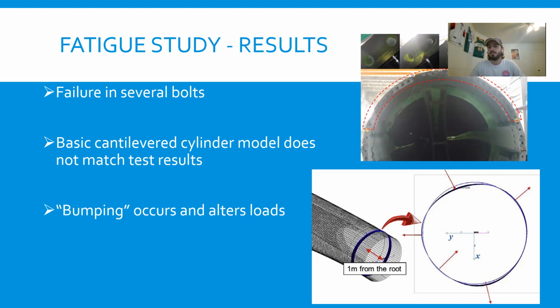During bumping, parts of the cross section of the root are getting elongated and stretched out, and some parts are getting pushed in, giving this weird circular shape shown in the bottom right. The parts that are getting pulled out from the circle are experiencing less load than the cylindrical model projects. And those that are getting pushed in are experiencing much greater loads than the cantilevered cylinder model expects. And that is what leads to the failing of these bolts that ended up being seen in the physical test.